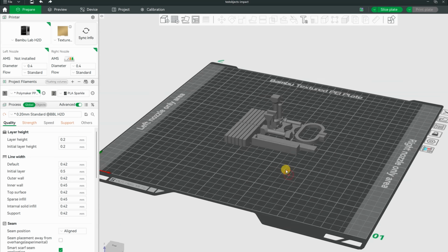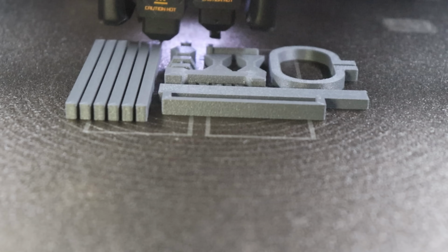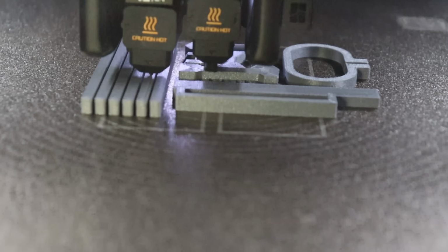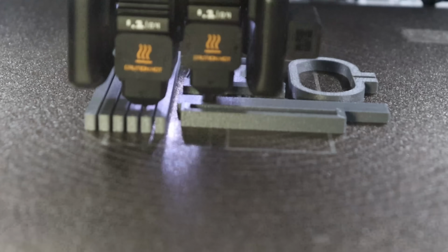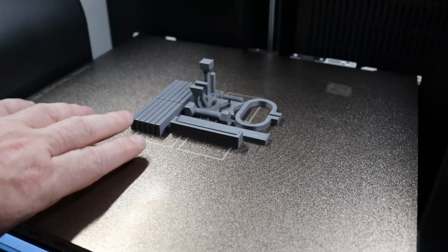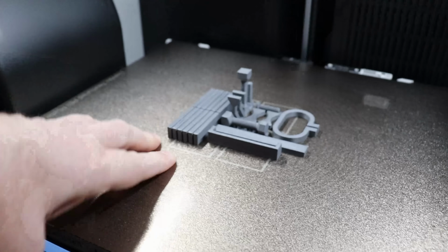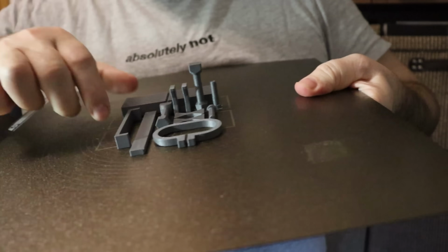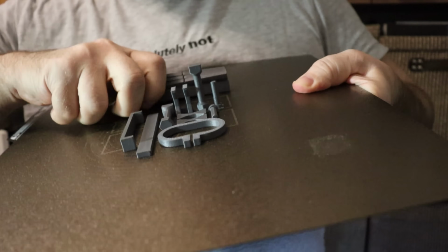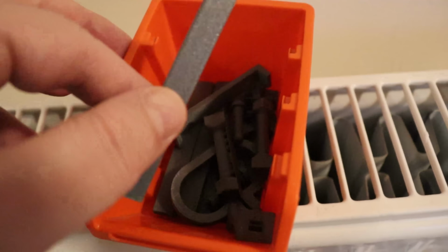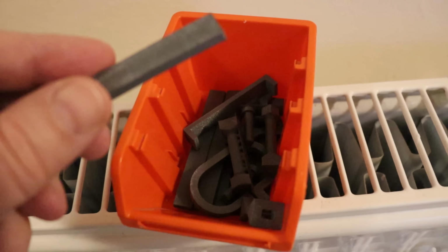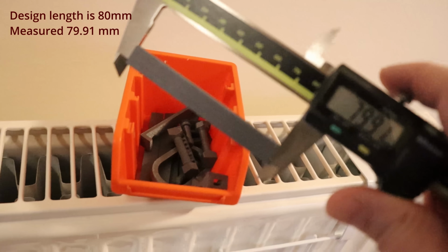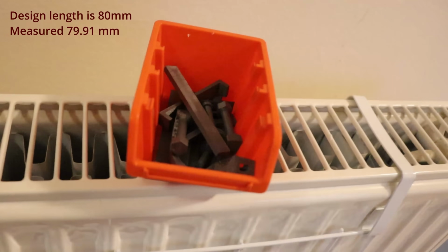My typical test objects. The printing is absolutely perfect, completely straight objects, no signs of warping. But the bed adhesion is still very strong. That's why in the later printings I reduced the first layer temperature to 320 degrees Celsius. Just quickly to check the shrinking. Thanks to fibers, this shrinking is very minimal and very accurate.